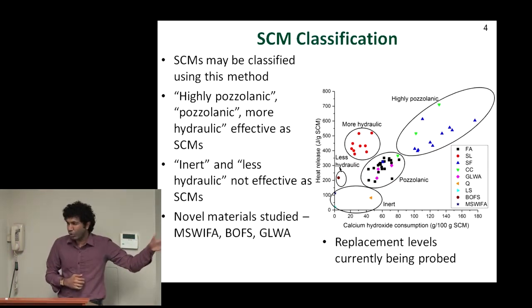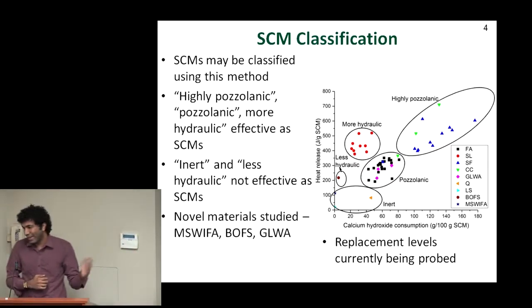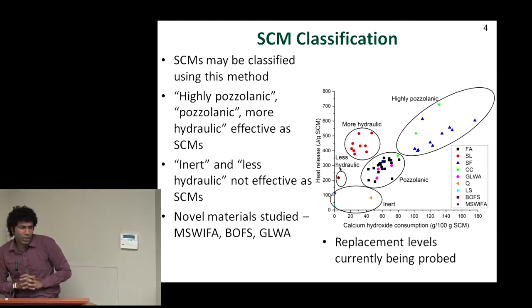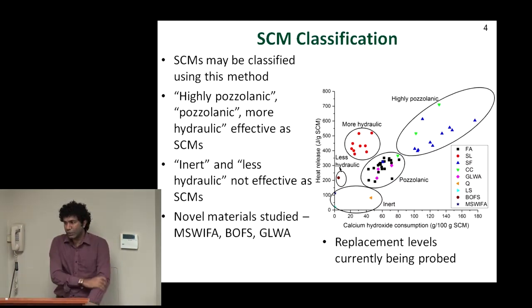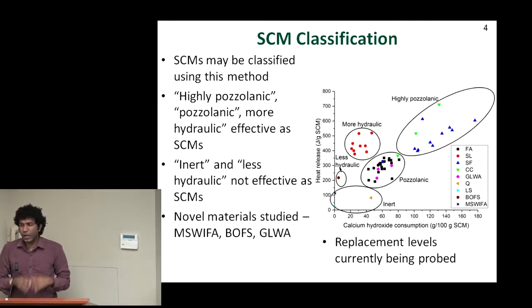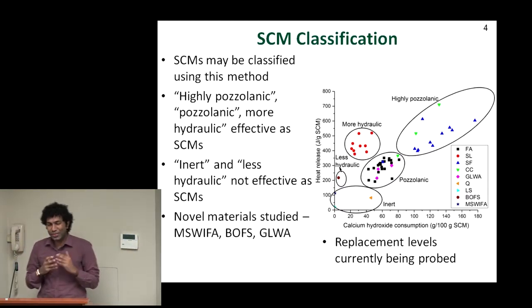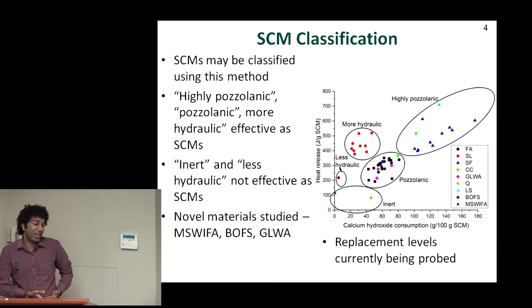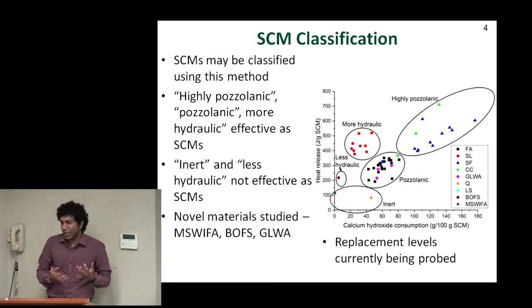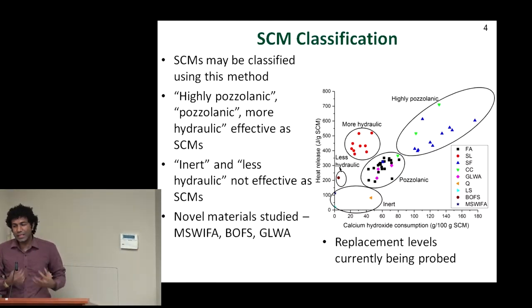This is from about 50 different materials, including about 10 or 11 different classes of materials. And what we see with this material classification system that we've developed is that you get about 5 or 6 different classifications of these materials. You have highly pozzolanic, more hydraulic, pozzolanic. These are good materials. We want to use them in concrete. Interestingly enough, almost all the conventional SCMs that we tested fall in that category. Not very surprising. And then we have inert, which is really not doing very much, and less hydraulic. And these, for the most part, are not that effective as supplementary cementitious materials.